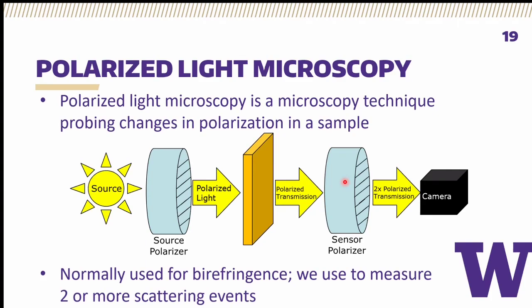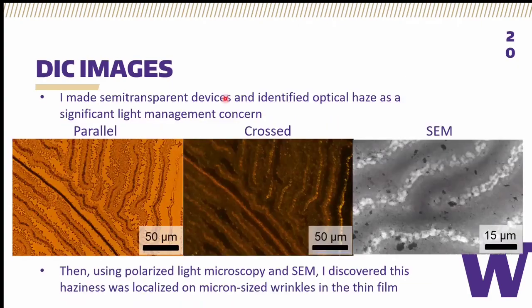We have neither nanowires in our sample, nor do we have an anisotropic crystal. Our crystal is perfectly cubic. And so if we were to see any image in the cross-polarized case, it would have to be a result of scattering, as scattering can randomize the polarization vector of incident light as this light goes through 2 or more scattering processes very efficiently. Indeed, we see that we get an image in the cross-polarized case.